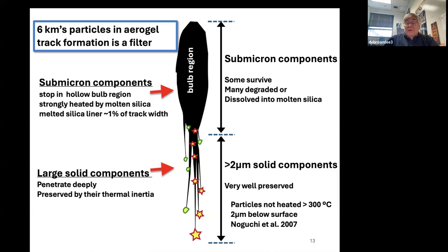Noguchi et al., doing experiments, predicted that particles captured down at the bottom are not heated above 300 degrees centigrade, just 2 microns below their surface. The time scale for this capture is really quick - a particle at this speed passes its own diameter in a billionth of a second, and the time scale of interaction with the aerogel is on the picosecond time scale. So the thermal wave does not penetrate very fast, very deep into particles.